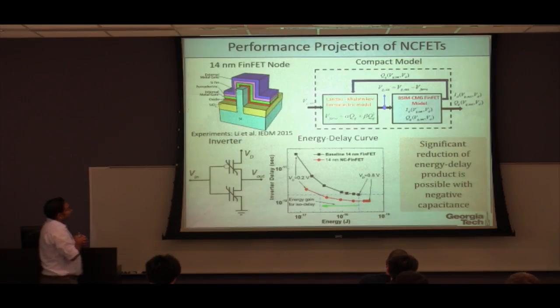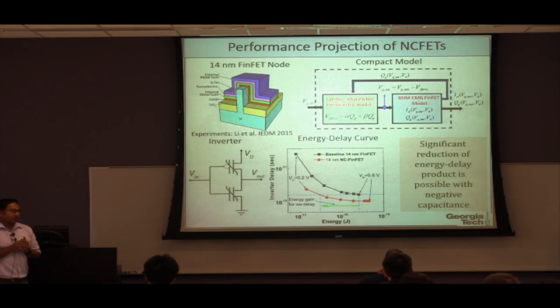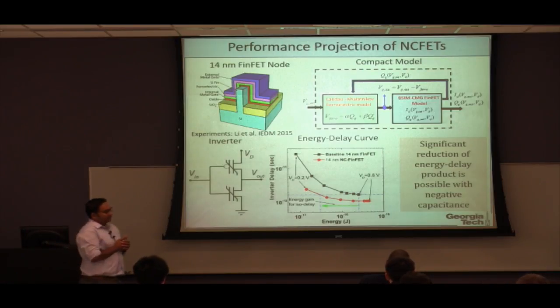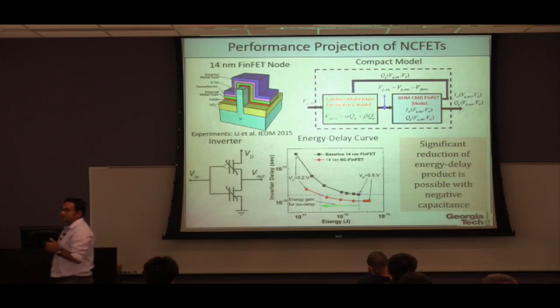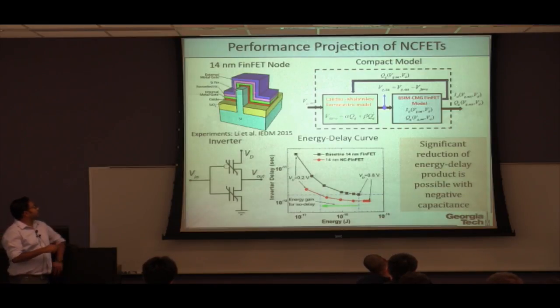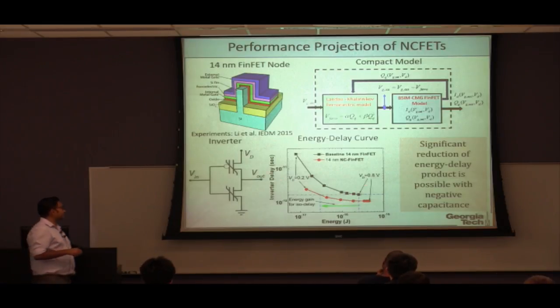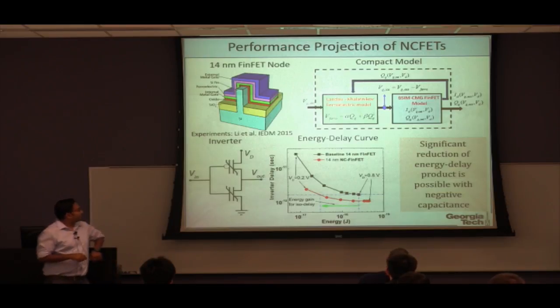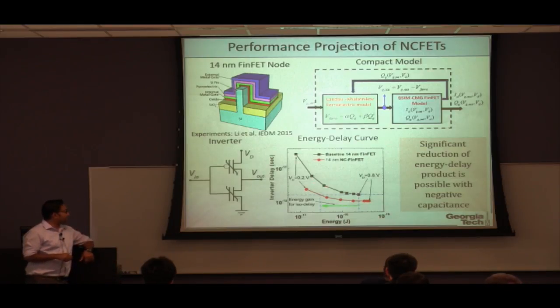All right, so now, what can negative capacitance transistors do for electronics? For that, we did performance projection of these kinds of devices. So we took a 14 nanometer node FinFET, and then we developed a compact model of this system. And when we plot the delay as a function of energy, we can show that without a ferroelectric, in a standard FinFET technology, the delay goes down. As you reduce the delay, the energy goes up.